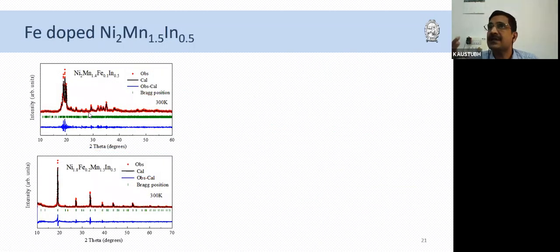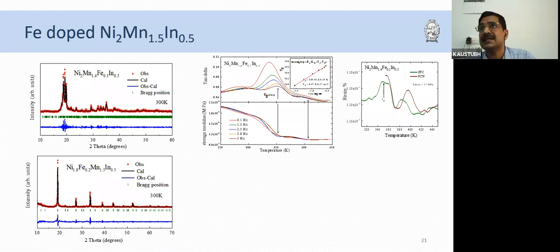So we looked at the structure, and I told you the structure of the strain glass phase should remain invariant. That means it should be the austenitic structure, the Heusler L21 structure. But we were in for a surprise. In the case of MnFe, the structure still remains martensitic, the 7M modulated structure. But in the case of NiFe, we see a cubic structure. Then we thought, okay, now we should look at the elastic properties and check whether there is a strain glass phase or not. And the surprise continued.